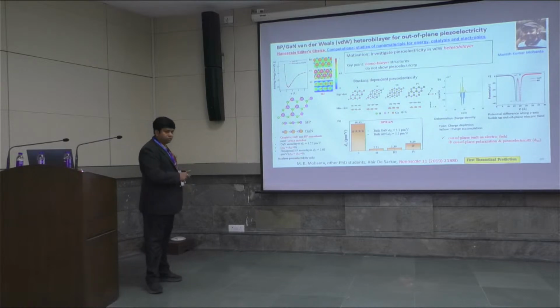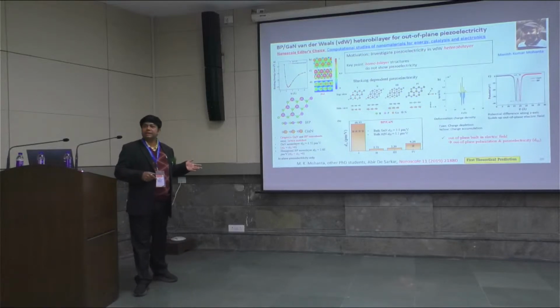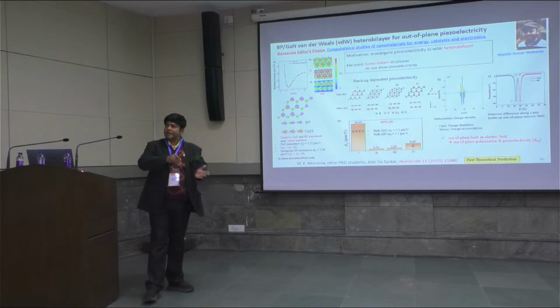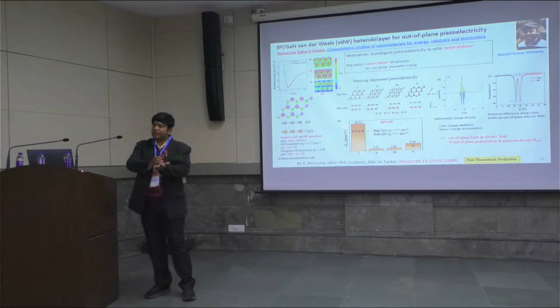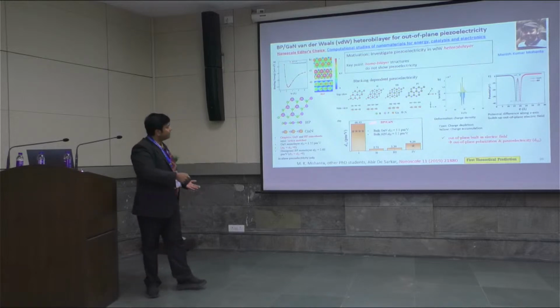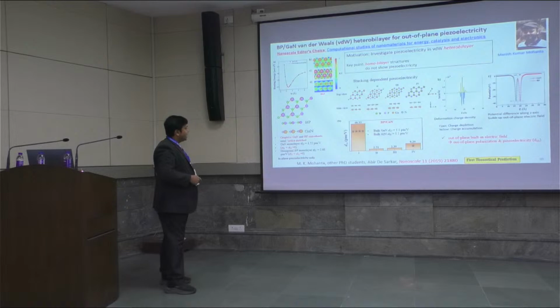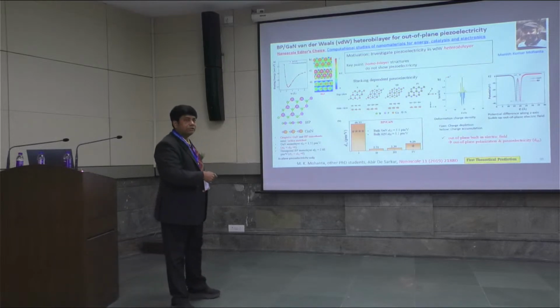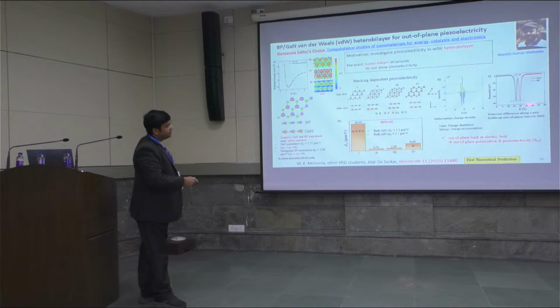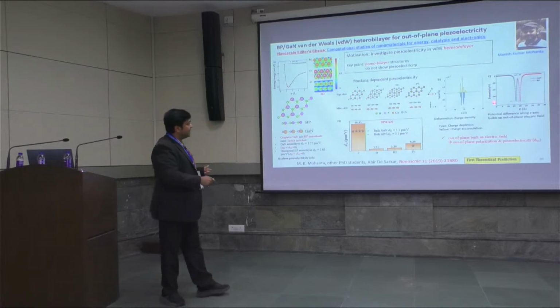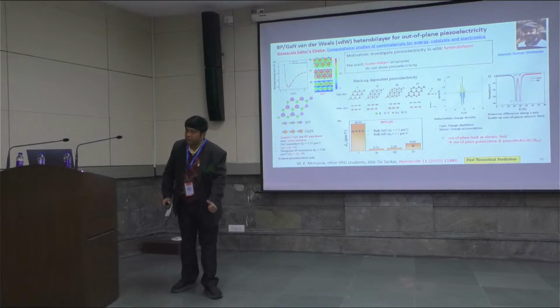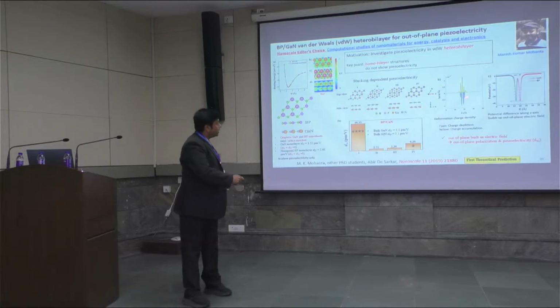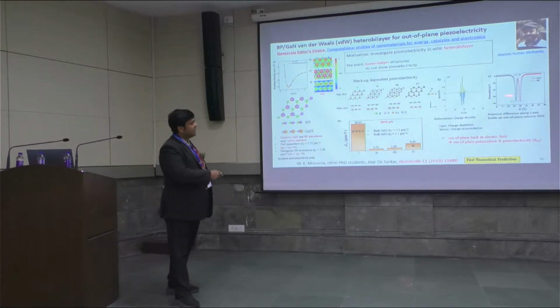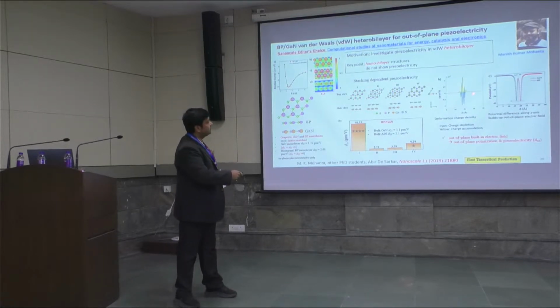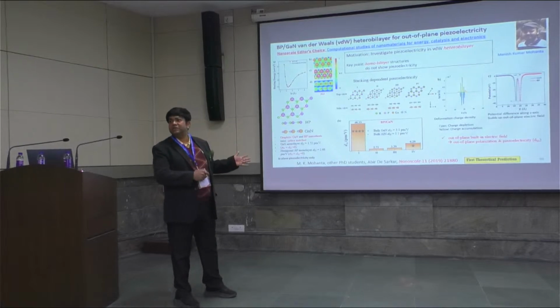When one is stacked on top of the other to form a van der Waals heterostructure, out-of-plane piezoelectricity arises, which is sensitive to the stacking order. When the layers are in perfect registry with one another, the interface dipoles are perfectly oriented along the z direction, and the highest level of out-of-plane piezoelectricity arises. We have then ascertained the origin of this out-of-plane piezoelectricity. It owes its origin to the difference in electrostatic potential between the individual monolayers. The negative gradient of this potential builds up an electric field along the z direction, an out-of-plane electric field, which polarizes the electronic cloud on the van der Waals heterobilayer, as is evident from the oscillations in the deformation charge density, alternating spatial regions of charge accumulation and charge depletion.